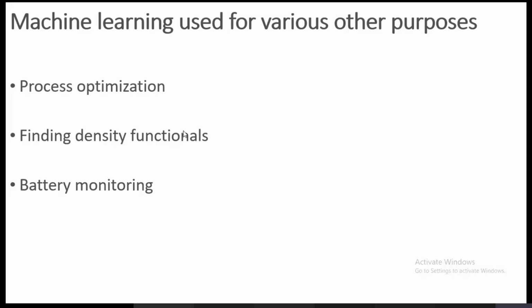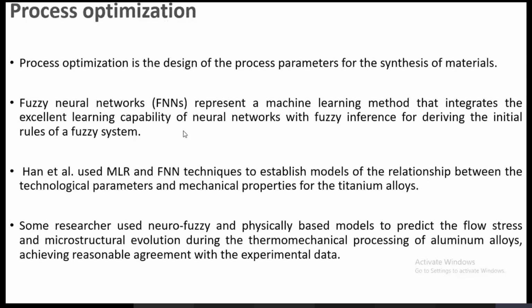Okay. Now here one scientist, Han et al., used multiple linear regression and fuzzy neural network techniques to establish the model of relationship between the input or process parameters and the mechanical properties of a titanium alloy, a titanium aluminum alloy basically. And some researchers also used neurofuzzy and physically based models to predict the flow stress and the microstructure evolution during the thermomechanical processing of aluminum alloys, achieving reasonable agreement with the experimental data.